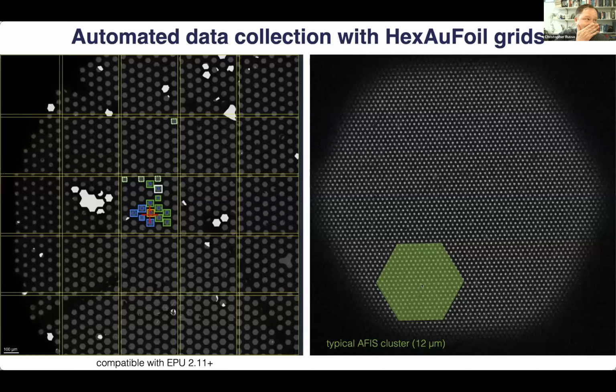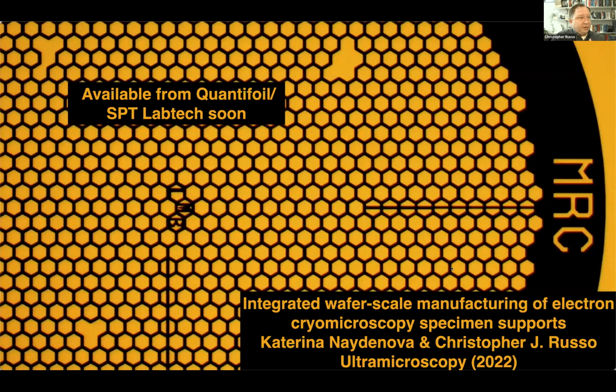So one of the other bottlenecks in cryo-EM these days is actually having enough good holes to image. The detectors are so fast and the microscopes are so fast that you can image thousands of holes per hour now. And so feeding the microscope enough good holes to look at turns out to be a limiting factor. But now we have increased the density of these by another factor of 10. So now each hexagon in this case, not square, has more than 5,000 holes. So you can get a complete data set from a single hexagon, whereas on a typical grid, you would only have about a couple hundred holes here. So we did commercialize this, and hopefully these are going to be available soon from SPT LabTech and Quantifoil.